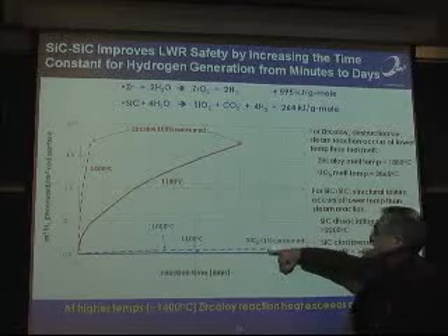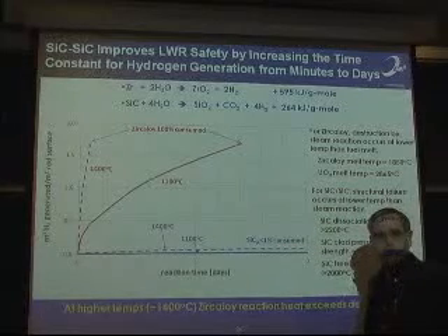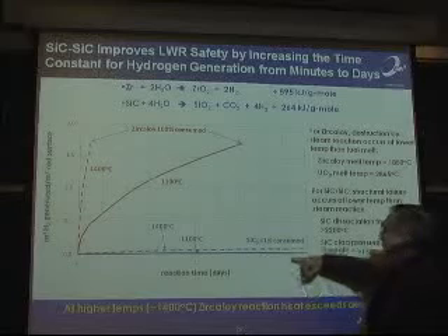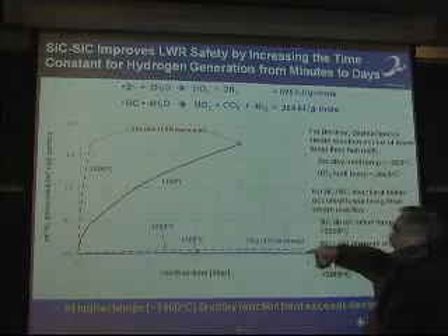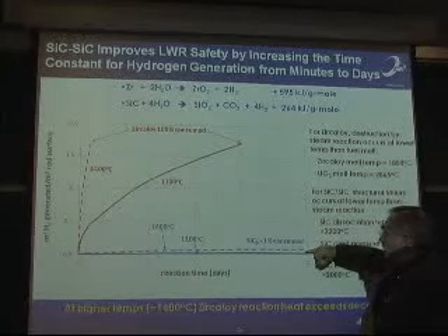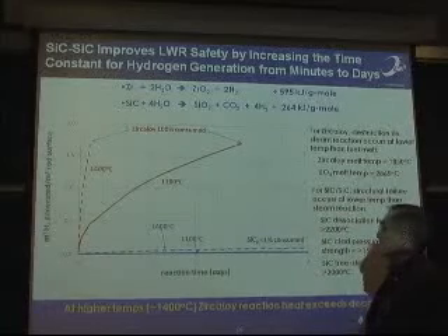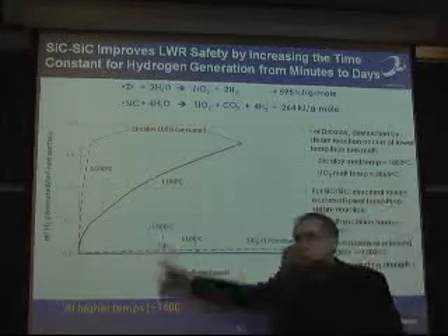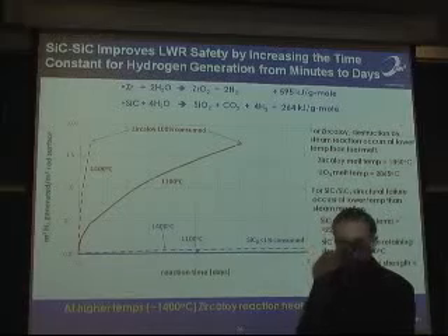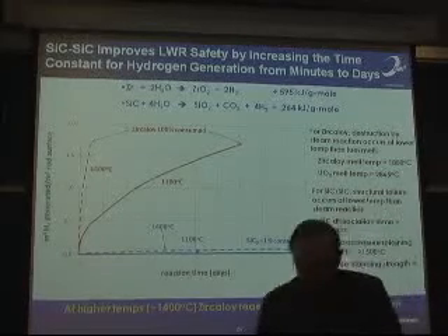With silicon carbide, well, it does react with water, but very, very slowly at these temperatures. And you can see after a couple of days, less than 1% of the silicon carbide would be consumed at 1400 degrees C. So that's the safety basis for this.